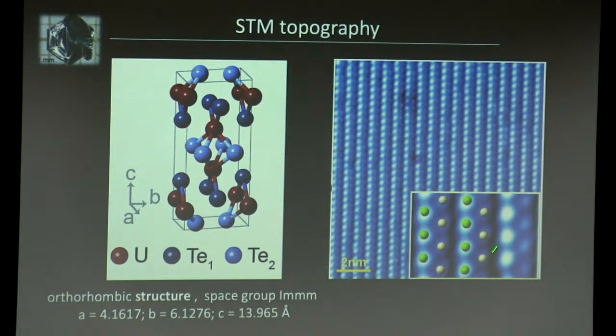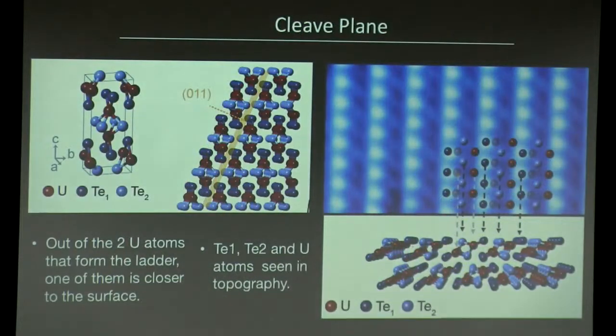This is what the topography looks like. As it turns out, this material cleaves along this very interesting direction, 0,1,1. We know this just by looking at the surface, measuring the distances between the atoms, and looking at the heights of the step edges.